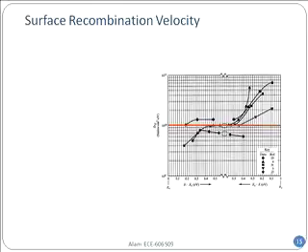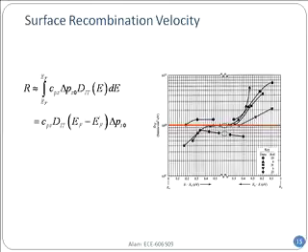And if I assume it's flat, if you want to put it in the computer and integrate properly, well, that's no rocket science either. But you can assume it's a constant. And then you are done. Then you see that all the traps between EF and EF prime multiplied by whatever is the average defect density, D sub IT. What is IT? Interface defects, at the interface or surface levels. And that's what you have.